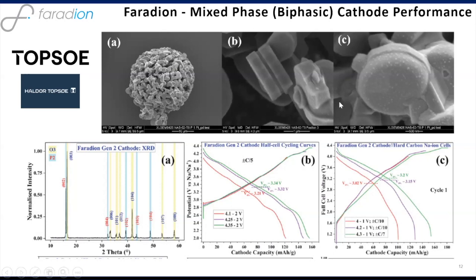And when we first saw these micrographs, typically the one on the right-hand side, we call this one the burger structure, where what we basically have here is the O3 layered oxide as the bun part of the burger, and then the patty being the P2. We also have the reverse situation in this micrograph shown in the center. And this particular biphasic material is around about two-thirds O3, one-third P2. And that gives us this benefit of high power capability, but also good high energy density as well.